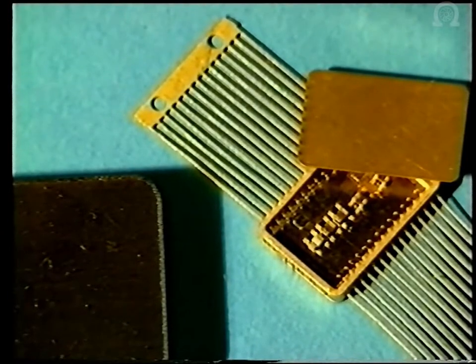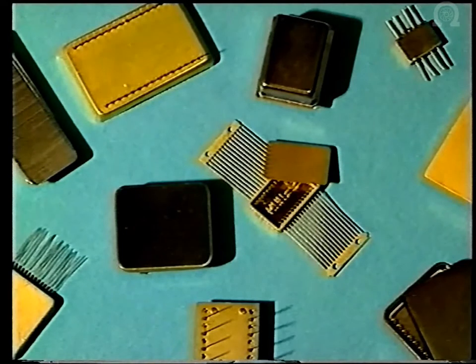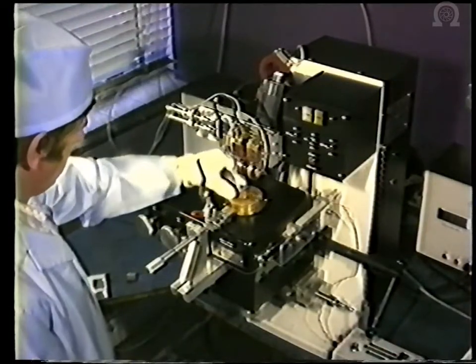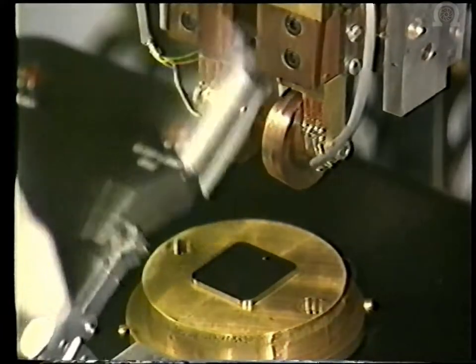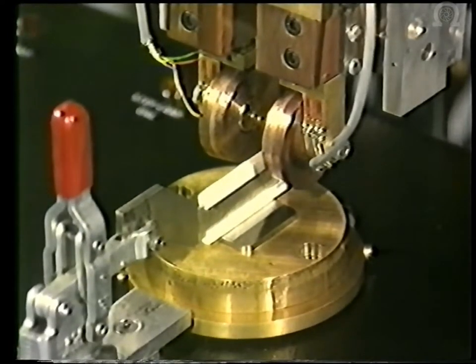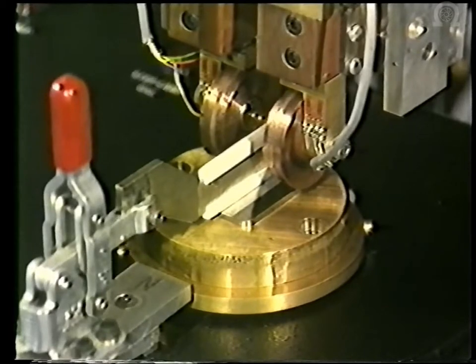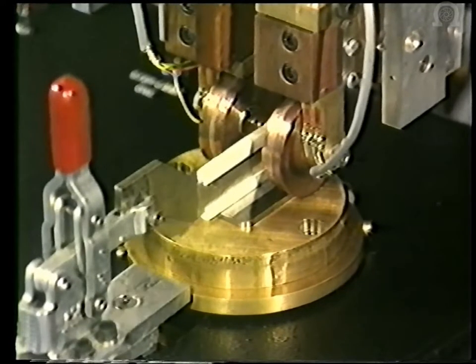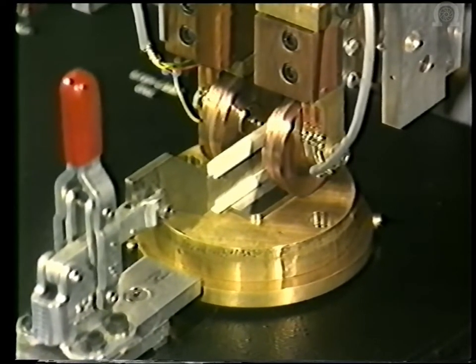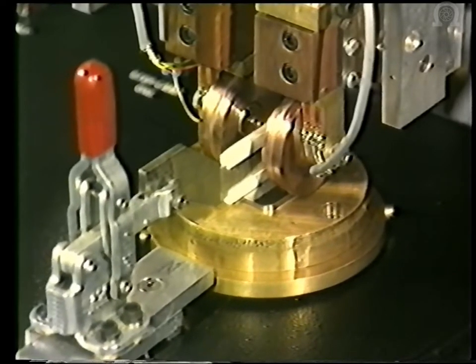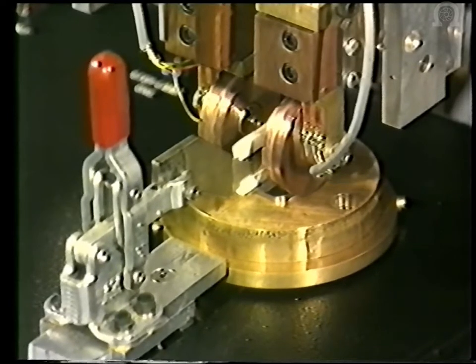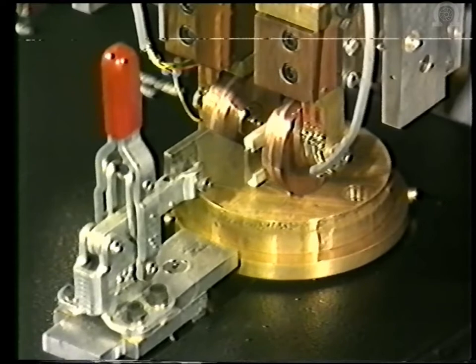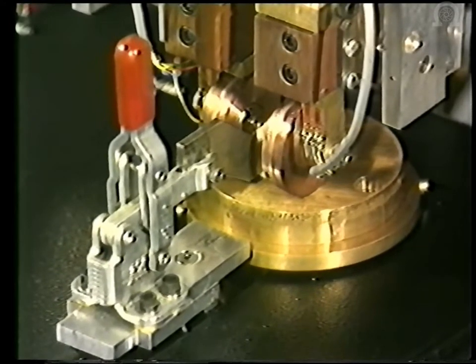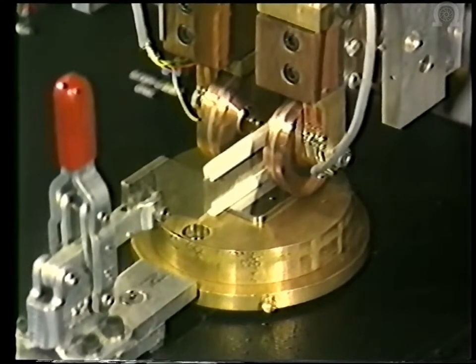Once devices have been interconnected, they are generally sealed inside a package which may be of plastic, ceramic or metal. Resistance seam sealing is a common technique for hermetically sealing large metal packages, which are often used in high reliability applications. Welding trials have been carried out on both gold and nickel plated Kovar packages with both stepped and flat lids. Helium leak tests, pressure tests and temperature measurements taken within the package during welding have been used to assess the joint quality and the possibility of damage to electronic components within the package. Metallurgical sectioning shows that the joint formed by this technique is not a fusion weld, but a braze formed using the plated coating.